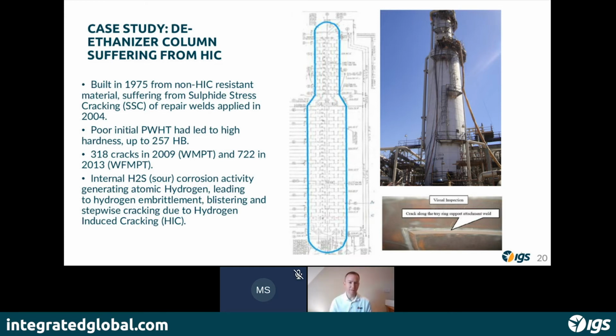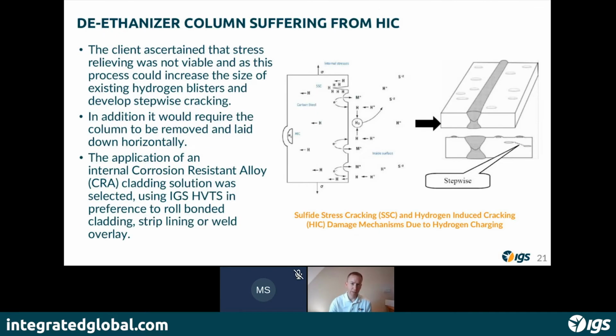And what they started to see over time was an increase in the amount of cracks, as you can see from the data on the left. And this suddenly jumped. In 2013, they decided they had to do something about this because they were seeing corrosive activity that was creating the atomic hydrogen that was then increasing the amount of these cracks and potentially leading to big challenges in terms of stepwise cracking and blistering.